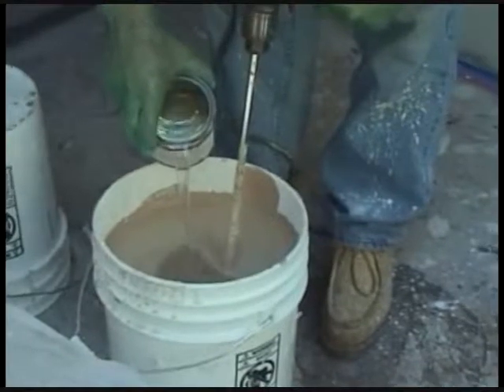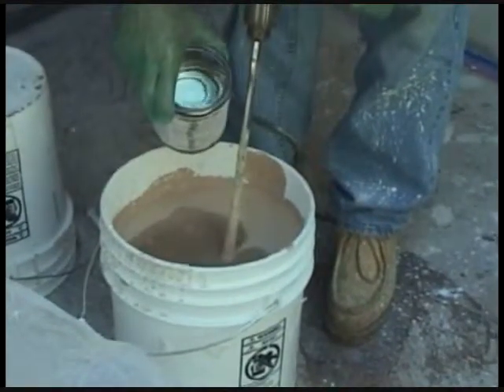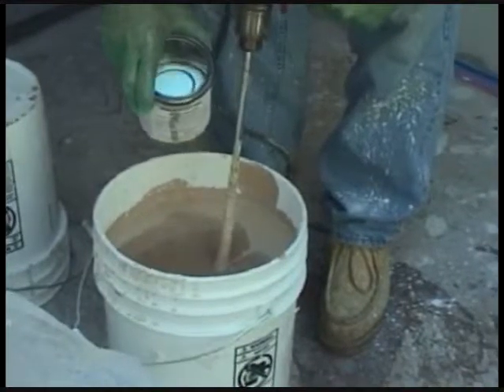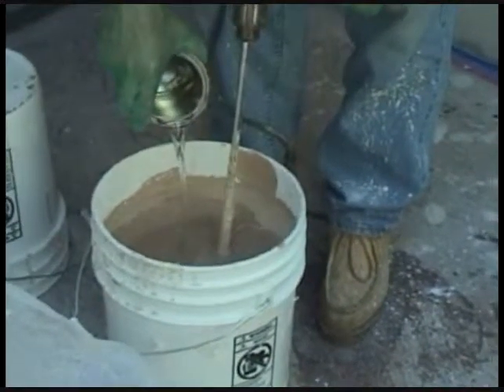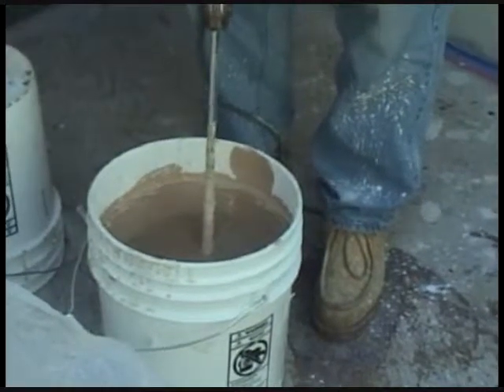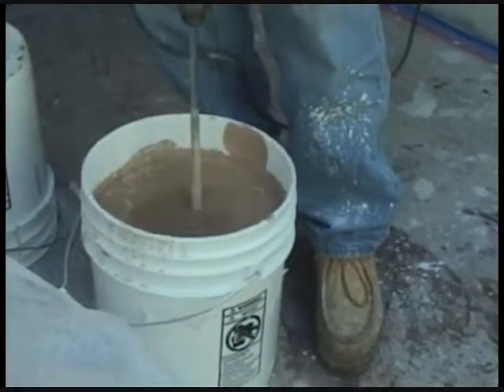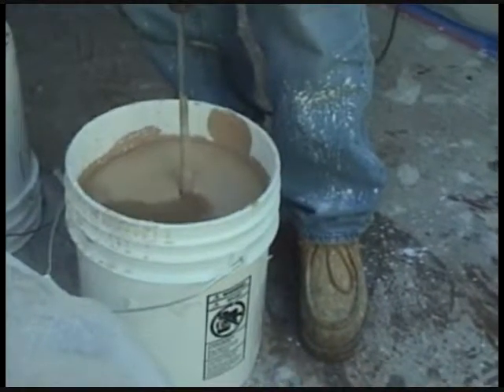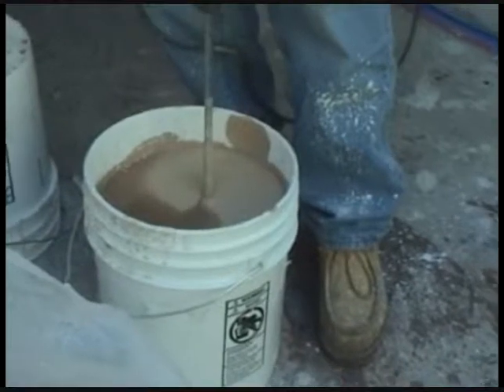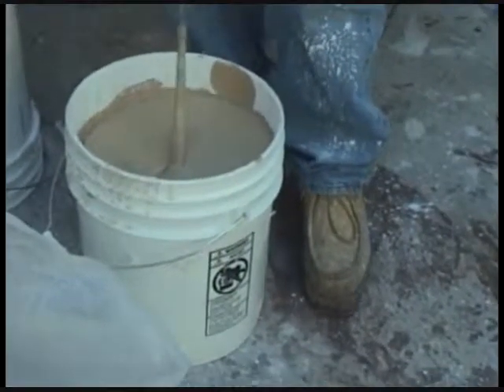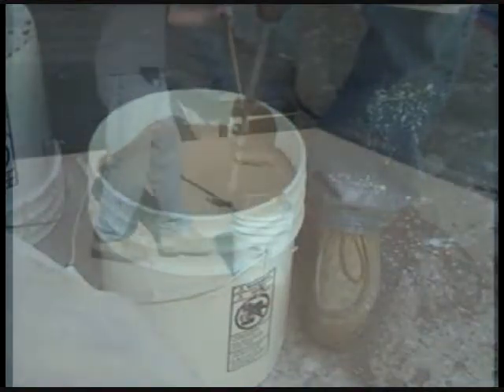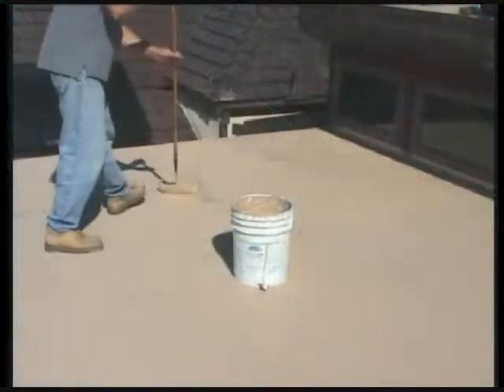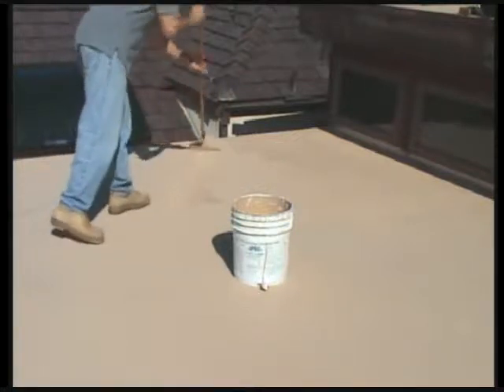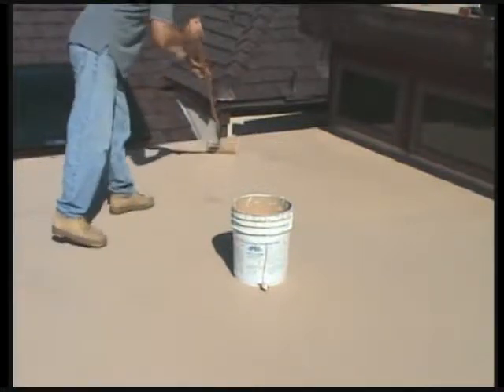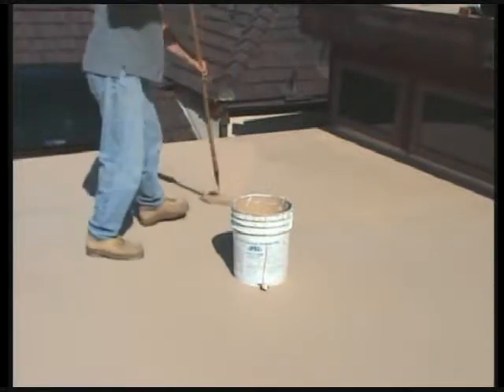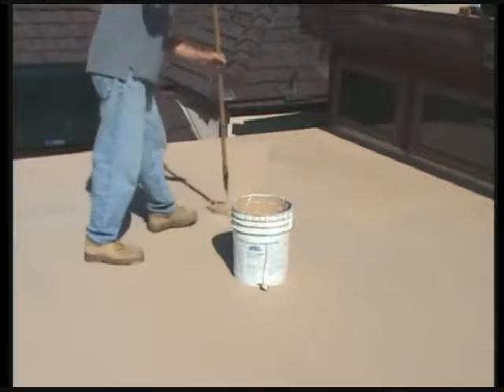He mixes a little at a time, keeping the paddle submerged into the coating. This is important not to entrap air into the coating so that you don't create bubbles at the deck level. The mixing occurs for about 3 to 5 minutes. Contractor takes a 3/8 inch nap roller, rolls the coating on at approximately 100 square feet per gallon. Contractor's not working the coating, he's simply rolling the coating on.